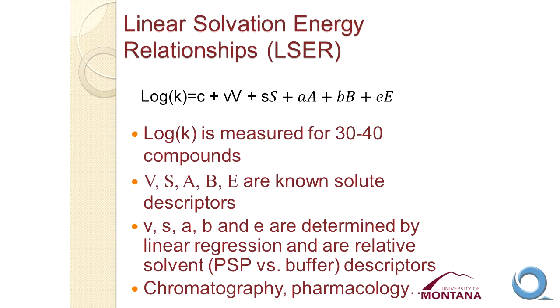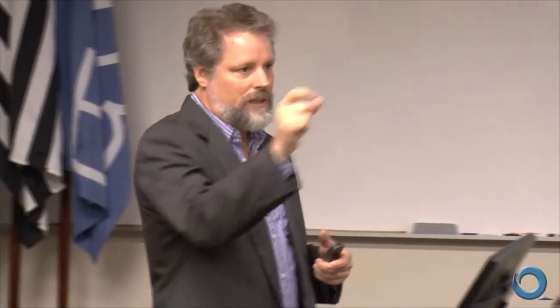One way that we use to characterize that is the so-called linear solvation energy relationship model. The basic idea here is that if we measure the retention factor and take the logarithm of the retention factor, that's proportional to the standard state free energy change when we go from the background electrolyte into the pseudostationary phase. So as an analyte, as a molecule, is transferred from the background electrolyte to the pseudostationary phase, there's a change in the standard state free energy, and this is proportional to that change. And then the idea is that that change in free energy is due to the sum of different types of chemical interactions that might be taking place.